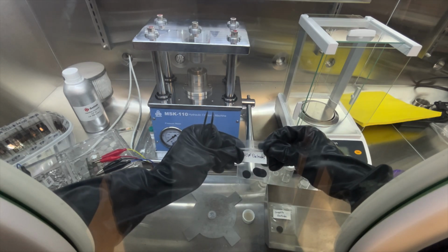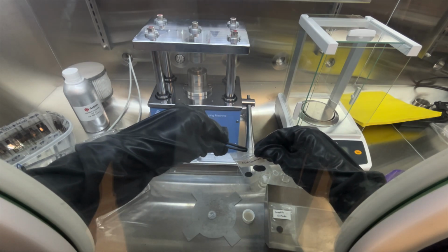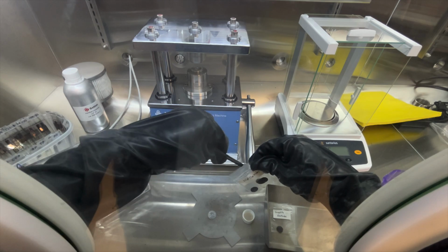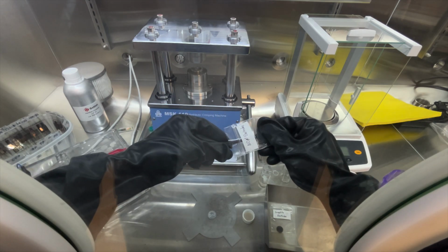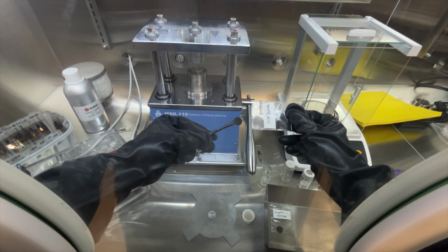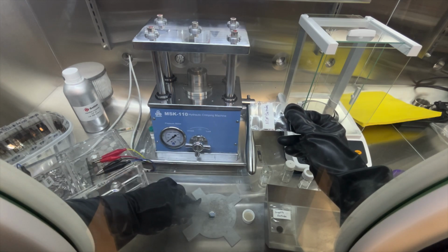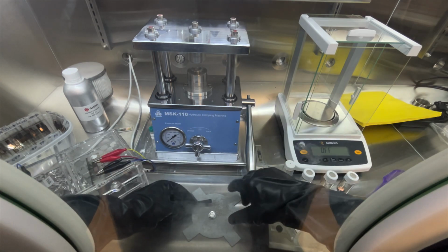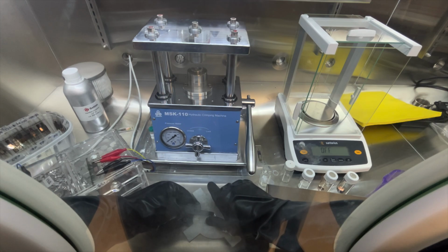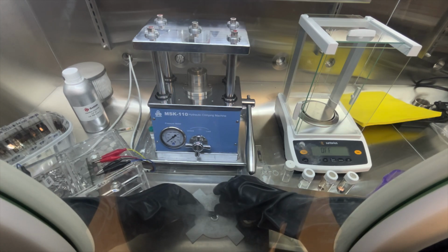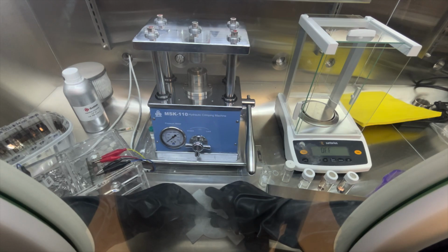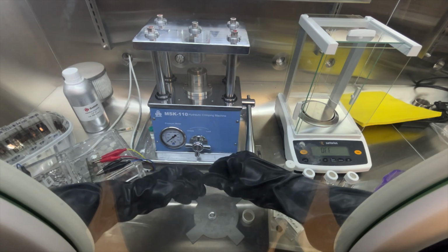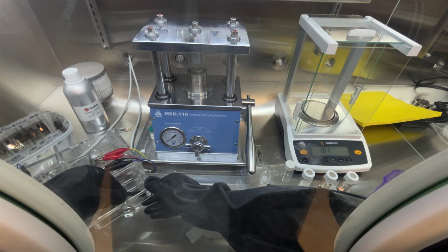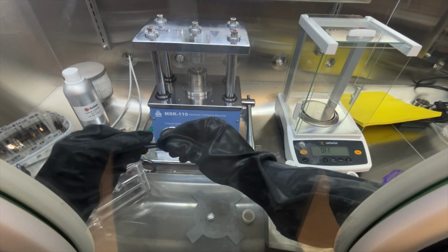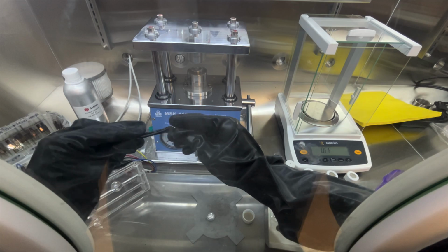Then I will add the NCM cathode, material side down so the material sides of both electrodes are facing each other and are in contact with the electrolyte-soaked separator. Once again, we will try to center it as much as possible, though primarily aiming to align it with the anode. We do this to maximize the surface area where reactions can occur on both sides of the battery. Continuing on, I also add in a second steel spacer.